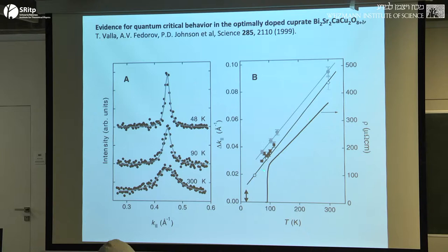the scattering rate that you would get interpreting this in terms of Boltzmann transport theory, these widths, quasiparticle widths, and the transport temperature dependence look more or less the same. So I don't know what that means, but that's certainly discouraging for hydrodynamics.